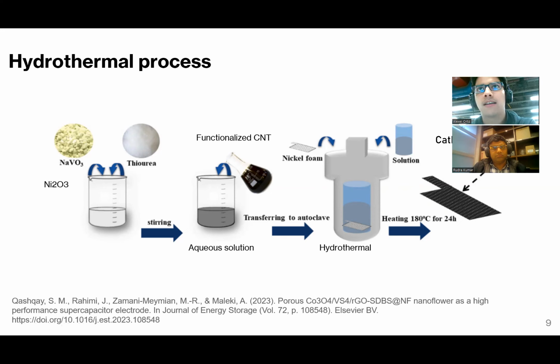nickel nitrate or sulfate, nickel chloride, nickel salt. Yeah, nickel salt, it's not a nickel oxide, it's nickel salt. So I'm going to change that later. We are also introducing the thiourea, that is the sulfide source, where we are going to extract the sulfide component, and here we have the vanadium salt.